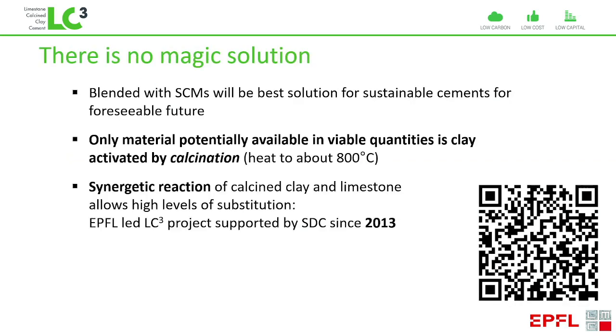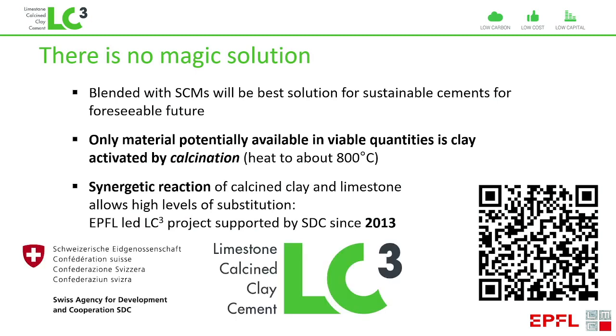So in a nutshell, the blended cements will be the most viable option for the future. And the only material which can extend this use of blended cement are calcined clays. And our discovery at EPFL was that we could have a synergistic reaction between limestone and calcined clay, which can allow us to go to very high levels of substitution. So we discovered this about 2008, and since 2013 we have been supported by the Swiss government through their Agency for Development and Cooperation to bring this technology to the industry.